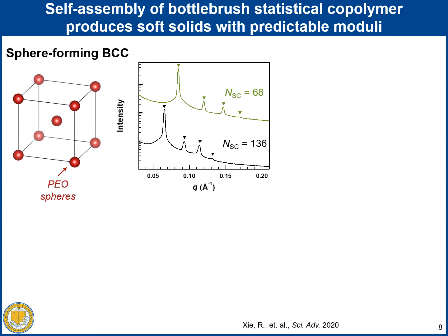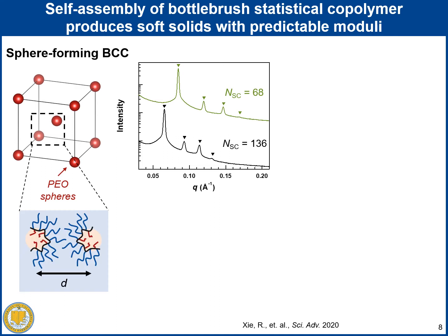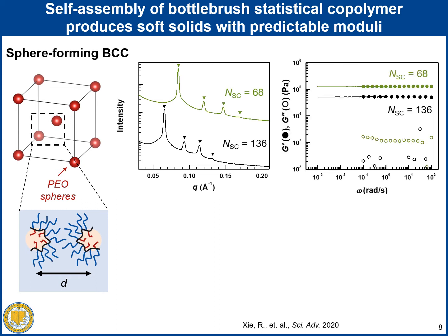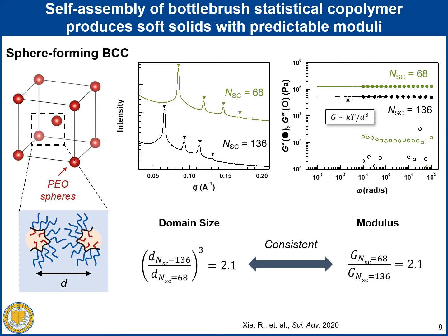First, we will demonstrate that the SAXS profiles collected at room temperature verify the expected Bragg reflection peaks for BCC morphology. And due to the unique self-assembly of bottlebrush statistical polymer, the domain spacing is actually controlled by the side chain length of PDMS, as indicated by the SAXS as well. Additionally, the corresponding structural modulus, which is represented by the frequency-independent storage modulus, can also be related to the domain spacing measured by SAXS. For BCC morphology, it's expected that the G modulus scales with the domain spacing to the power of 3. Indeed, for these two samples with different side chain length, the expected scaling is obeyed. Therefore, this relationship allows predicting the moduli of a self-assembled bottlebrush statistical polymer.